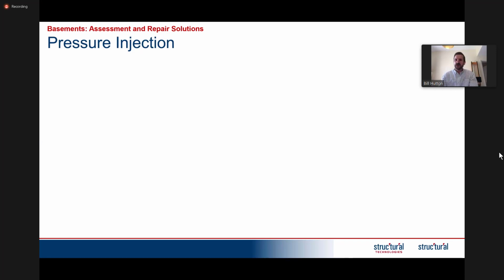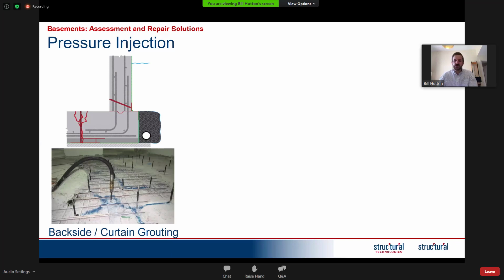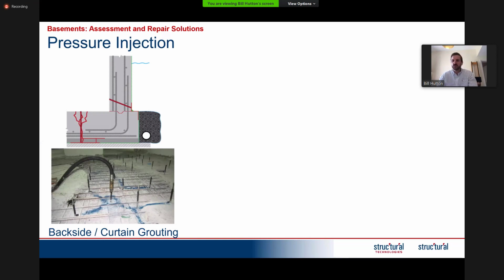So we'll start off by having a brief discussion on pressure injection. So we're going to talk about two basic concepts today, or means of doing pressure injection. So the first would be what we call backside or curtain grouting. So what we're doing here is we're actually drilling almost completely through the member. So if it's a wall, we're drilling almost to the back of the wall until we leave about 10 millimeters of concrete. We would then put a steel bar or steel rod down into that hole. We would tap it, we would fracture the concrete, and you would actually pump injection material.